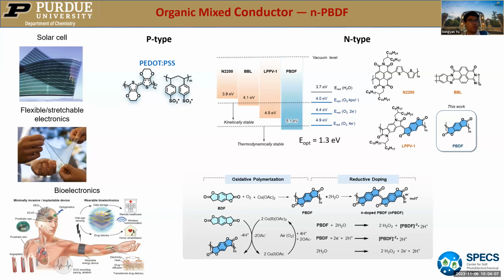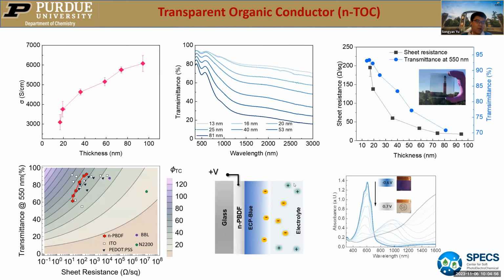Recently in our group, we reported a new n-type material called n-PBDF. It has state-of-the-art conductivity and performance compared with previously reported n-type materials. It has a conjugated, planar polymer backbone. The benefit of this is that it has a very low LUMO level, so it will be stable under ambient conditions like water or oxygen. So it will be conductive just in air. I'm not going to introduce the synthetic work because I'm not a synthetic chemist. It's a very fancy material, and it has the highest reported conductivity, even higher than PEDOT:PSS.